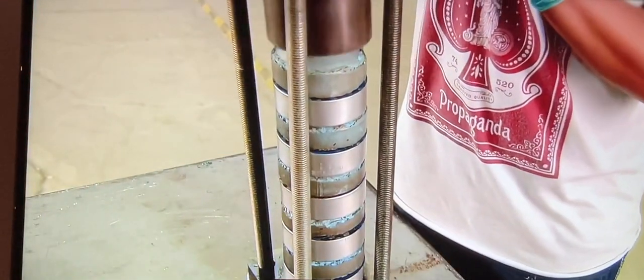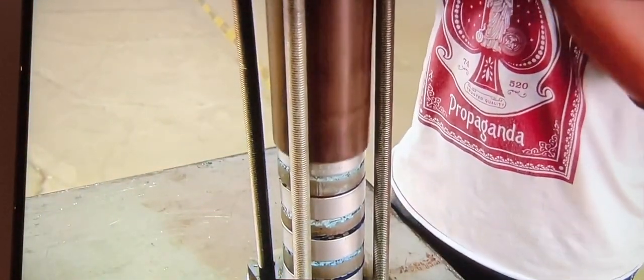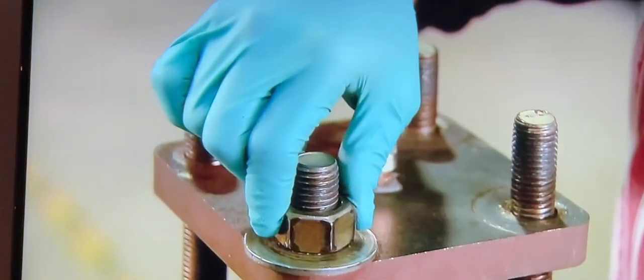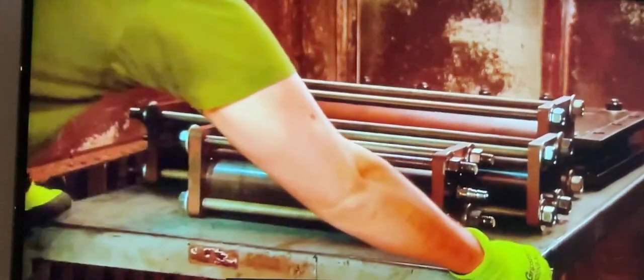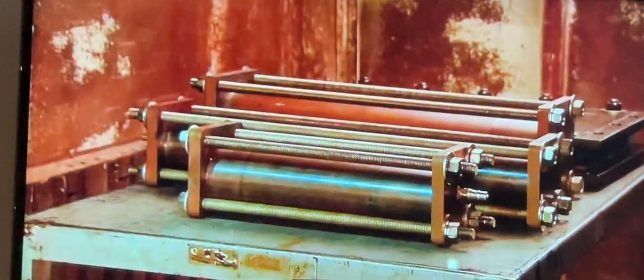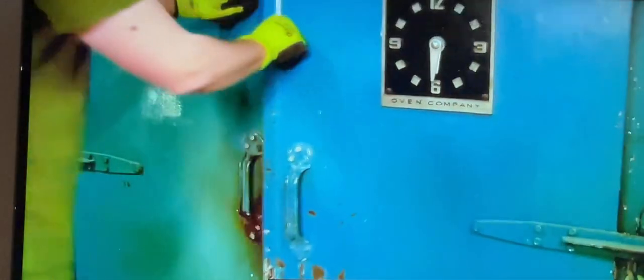She stacks the flanges and slides a tube around them. She bolts on a lid. Then it's into an oven to bake under pressure for about 4 hours. This transforms each patchwork of carbon fiber into a solid, seamless bike wheel flange.